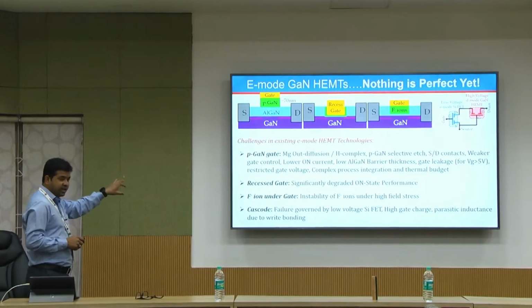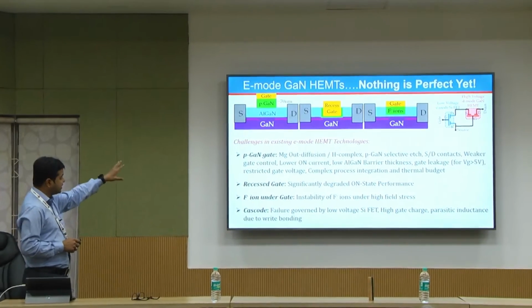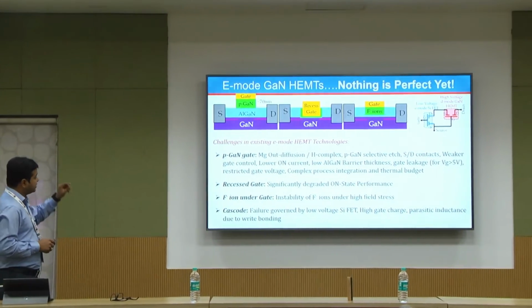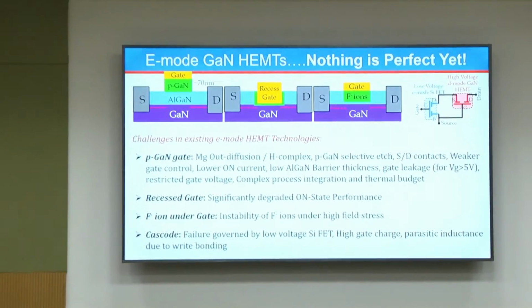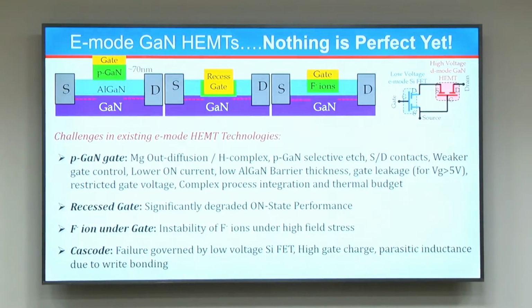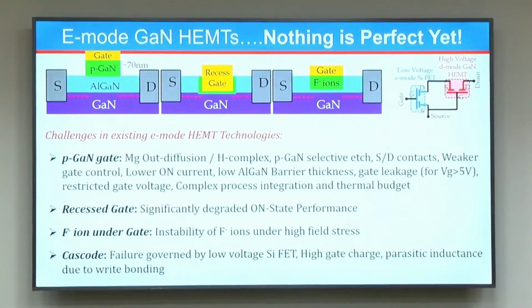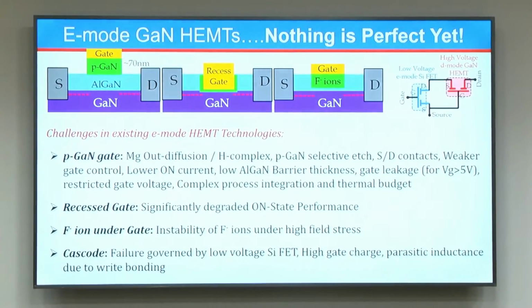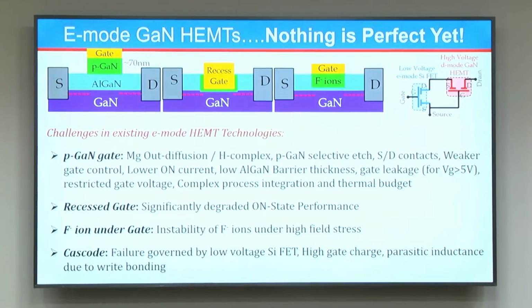You have pGaN gate based transistor technology, the first one that you see here. This uses a pGaN. So basically you grow the AlGaN stack with a pGaN cap on top. Typically it's a 70 to 80 nanometer pGaN cap with doping concentrations in the range of a few E18 to 1E19. Active concentration would be around 1E17 to 3E17, right? Now this depletes the 2DEG and you basically realize these enhancement mode devices.